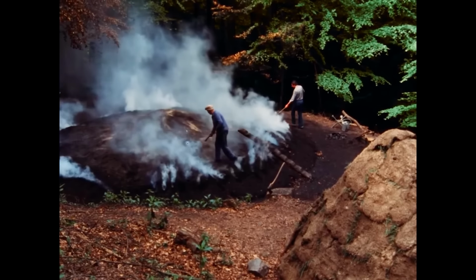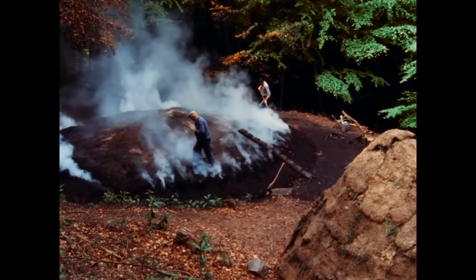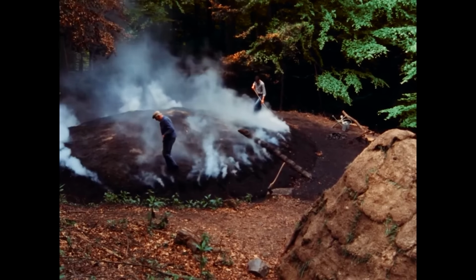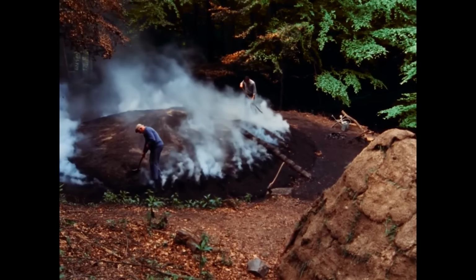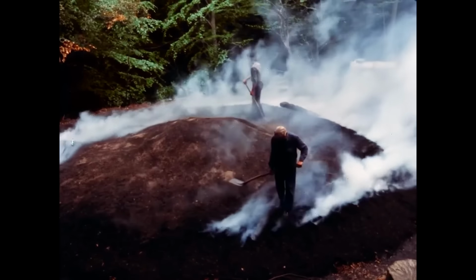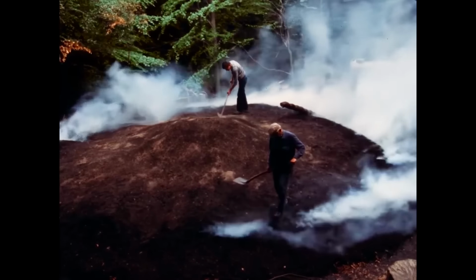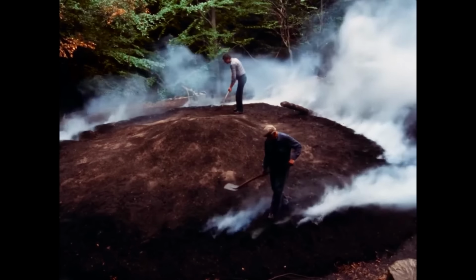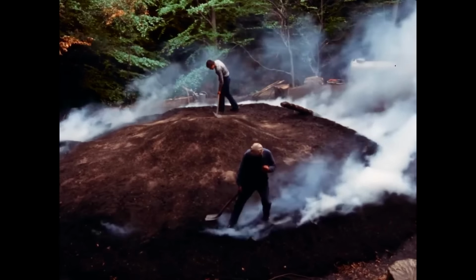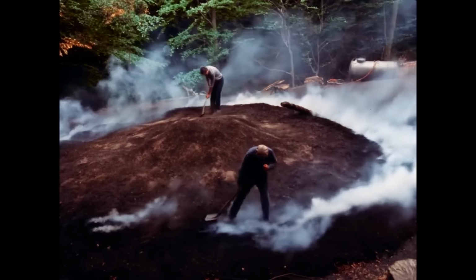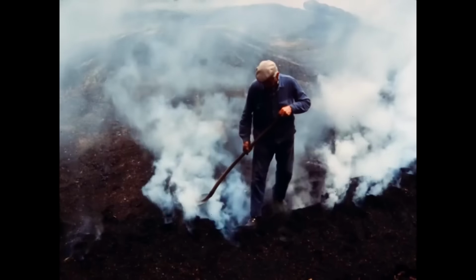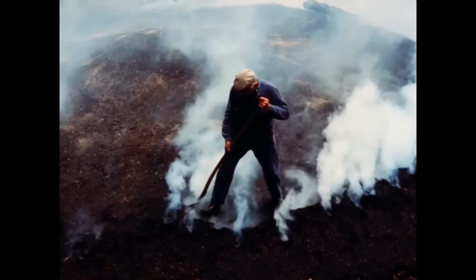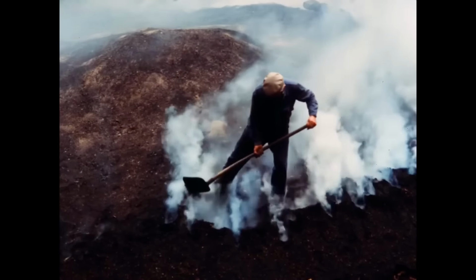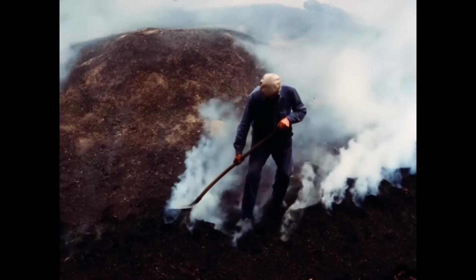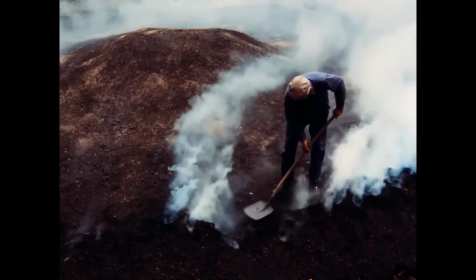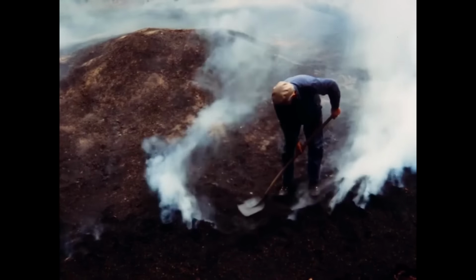Weather plays a critical role in kiln charcoal making. Ideal conditions are dry days with moderate breeze. In hot, still weather, the kiln gets too little oxygen. It won't draw. Strong winds supply too much oxygen, causing uneven charring or even ignition. Entire kilns often burned because the danger went unnoticed. Such fires can barely be put out and easily spread through the surrounding forest.